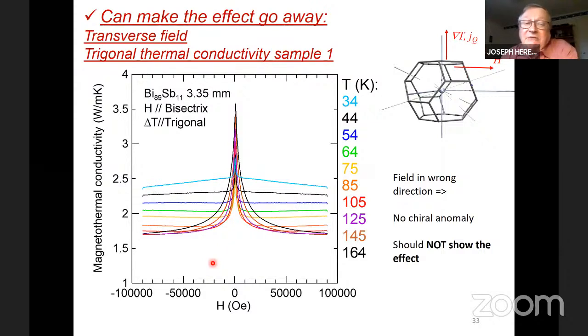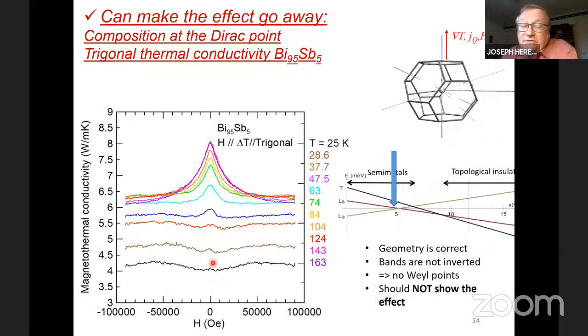Can we make the effect go away? Well, of course, if we put the magnetic field in the wrong direction where we don't form Weyl points, we have no effect. And we also don't have a grad T dot B term here. We only have a grad T cross. And the other thing that I already showed you is if we take a sample that is not a Weyl semi-metal, but a conventional semi-metal with trivial pockets at T points, there is no such effect. If we do the same longitudinal magnetoresistance experiment, there is no effect. So we think the effect is really correlated with the Weyl state of the material.